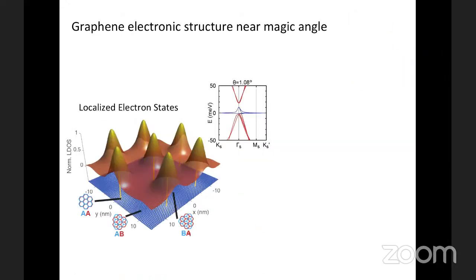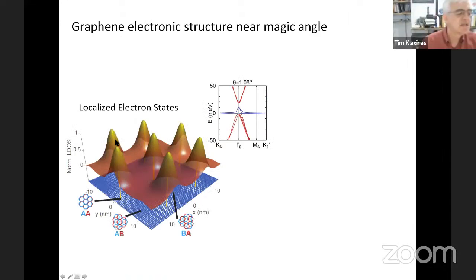Thanks. Okay. So this is a picture now of the localized electron states in real space. And I hope this will answer one of the questions that came up at the end of the previous talk. So this down here is the bilayer graphene. These indicate the regions of AB stacking here, BA stacking here, and AA stacking here. And the vertical axis here is the local density of states, of electronic states in real space. So this is where the electrons actually really reside in real space. And as you see, they are strongly localized at the AA sites, right around here. And this has important consequences, and I will come back to it. And these are the flat bands at 1.08 degrees.